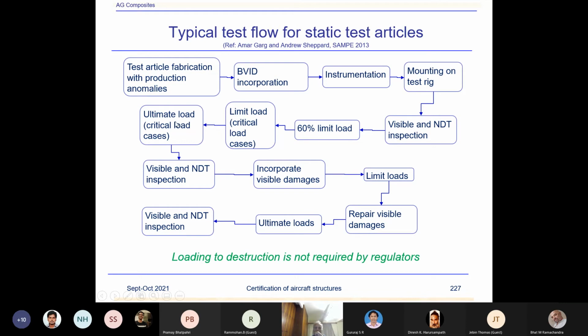And then once you are loaded to ultimate, that means it has met that compliance, the first zone or category 1 damage. Then you have to create visible damages, like VIDs. So we created larger impactor damages and also machined some notches and holes. Then visible and NDT inspections, and incorporate visible damages, and then load it to the requirement for visible damages. Residual strength requirement is the limit load. So here we are loading to only limit load, not to ultimate load.